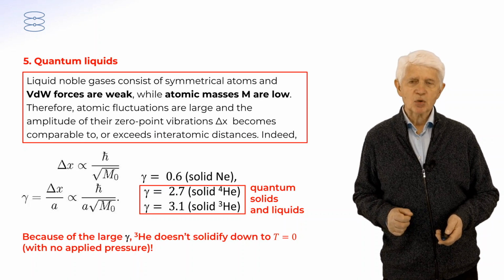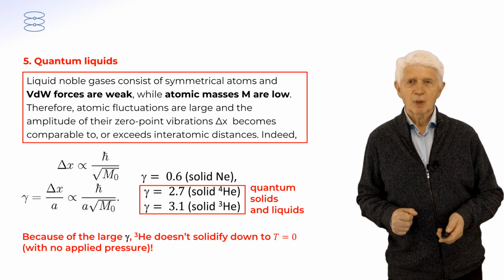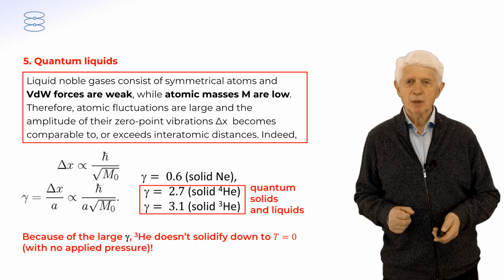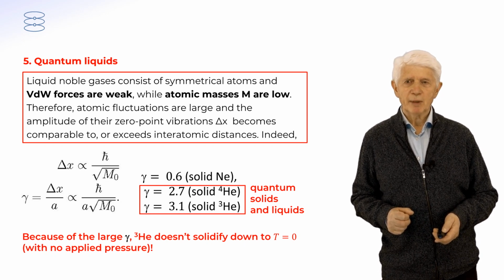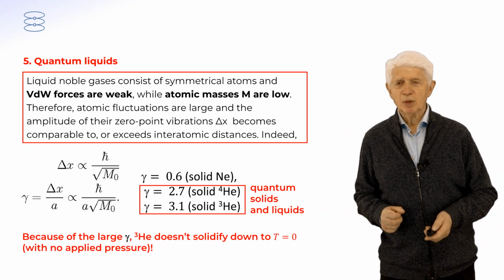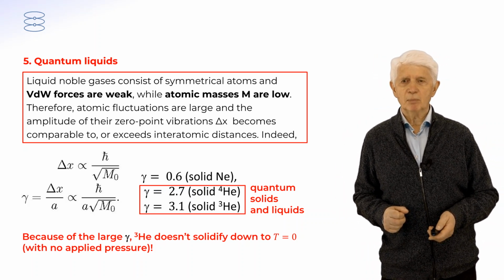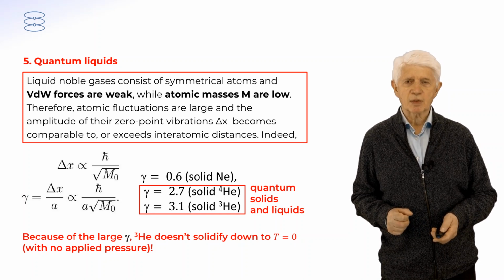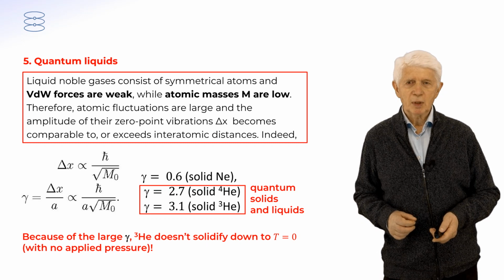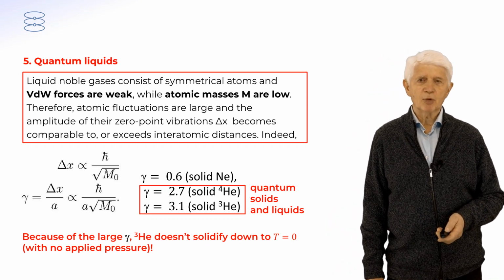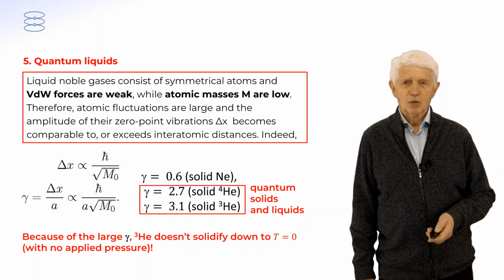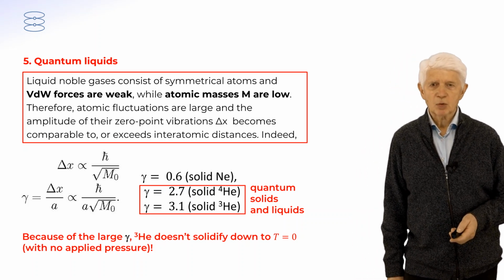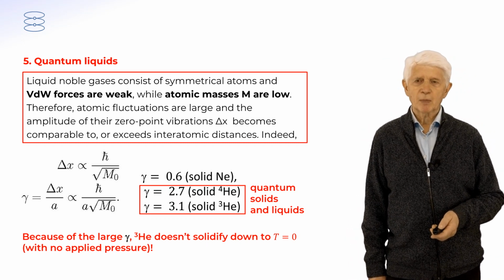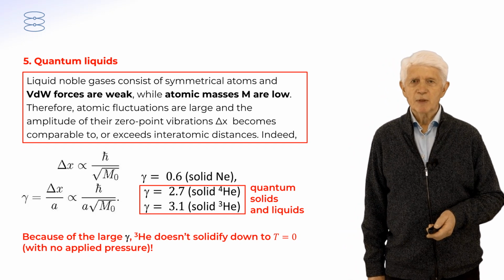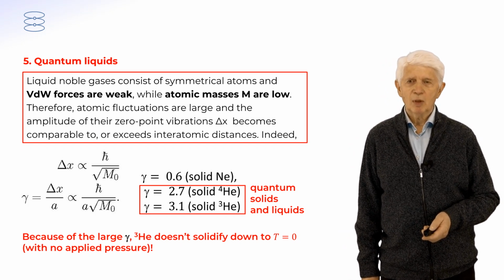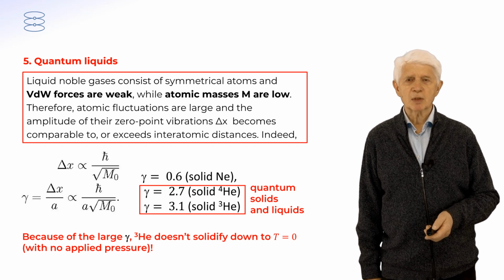Whereas the dimensionless ratio of the amplitude of vibrations to the interatomic distance is gamma equals h bar over a square root of m naught. The interatomic distance a, as we said, is about the same in all liquids and solids. It's about 1 angstrom. If we put some figures, then we immediately find that gamma is equal to 0.6 for solid neon. But for solid helium-4 and solid helium-3, gamma is bigger than unity. It means that the amplitude of the zero-point vibrations, their quantum vibrations, is bigger than the interatomic distance.